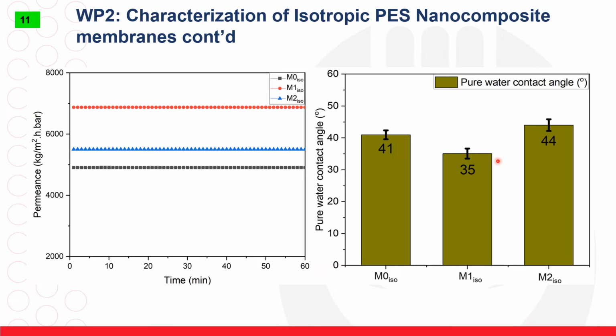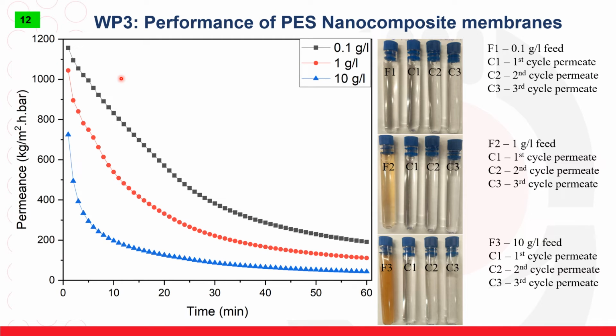The mixed phase molybdenum disulfide nanosheets made the resultant polyether sulfone composite membrane hydrophilic, as evidenced by the low contact angle, and the single phase made the membrane hydrophobic. And this affected the pure water permeance, whereby the mixed phase had a higher pure water permeance, whereas the single phase molybdenum disulfide blended with polyether sulfone had a very low water permeance. The permeance of different concentrations of synthetic oily wastewater was different, and as can be seen, 0.1 grams per liter had a higher permeance as compared to 10 grams per liter.